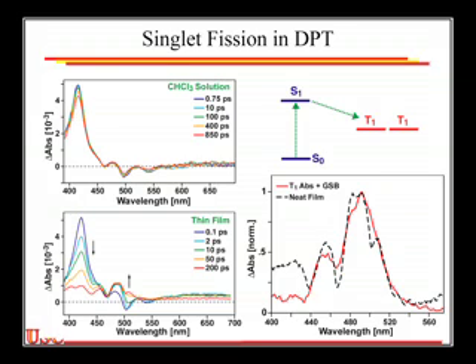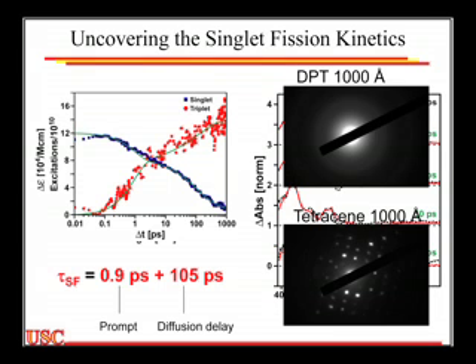It's doing singlet fission, and we can measure the rate of this process pretty well. Because again, I can fit this to a combination of singlets and triplets as time goes out. I can measure the rates, and I get two rates. It's a bi-exponential rate. I get about 0.9 picoseconds and about 105 picoseconds. And so we're having a very prompt one. This is about the rate people expect for singlet fission in crystalline materials. It's sub-picosecond, anywhere from 500 femtoseconds to about a picosecond.